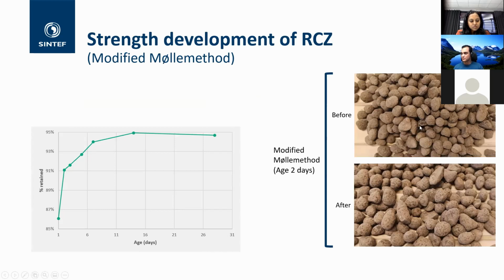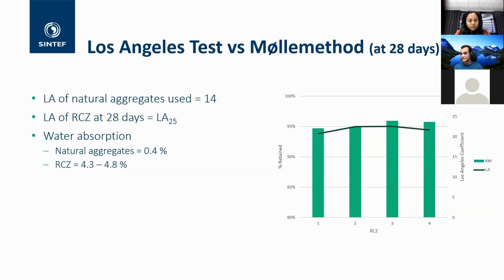The pictures on the top are before the test with the modified Molle method, and on the bottom is after the test, on aggregates at the age of 2 days. And with this method, we tracked the development of strength in the aggregates, or to rephrase, we tracked how much of the aggregates is retained on a 2 millimeter sieve. And when we plot it, it has a very good correlation with the development of strength of concrete. And it should, if our test method is working, because the aggregates are basically concrete, which is hardening over time. And this was a very good indication that the test method that we modified is working very well for our purpose.